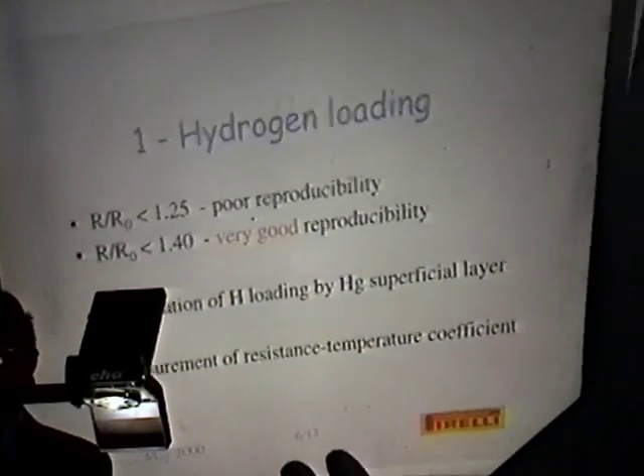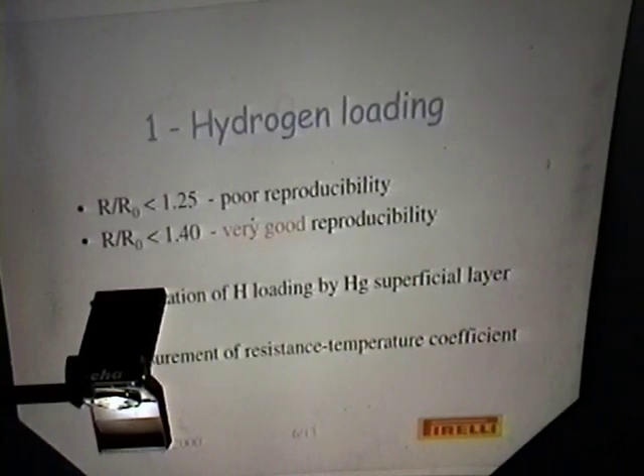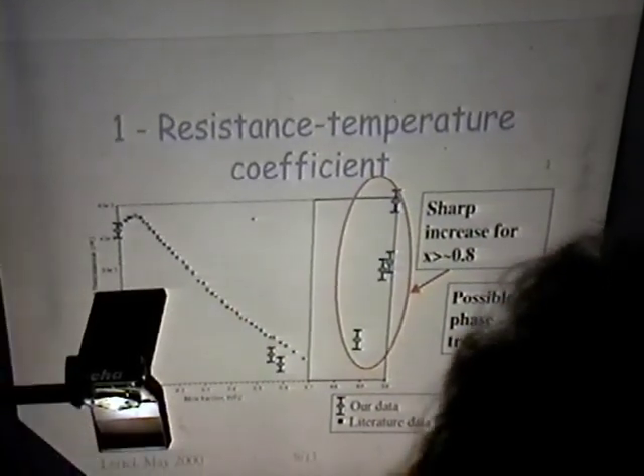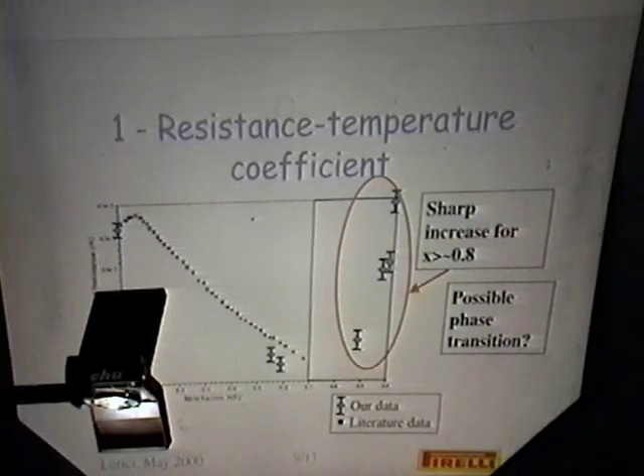This possibility to keep the wire loaded also after electrolysis in air permits to measure various, in theory, various physical quantities of the highly loaded palladium. The easiest to measure is the resistance temperature coefficient, and we've done such measurement for the 3 wires I have just shown you. This is the result. There is a sharp increase in this value, as pointed out yesterday by Celani, and this is a possible indication of a phase transition.